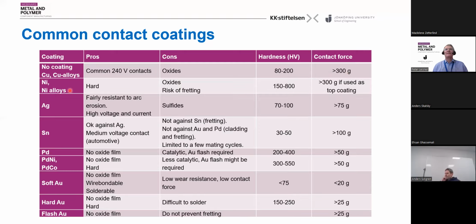Then you can use a nickel coating or nickel alloy coating. And again, talking about nickel and nickel alloys, it's a big difference in hardness and properties of these. Anders will come back to this in more detail. But these are relatively hard or hard coatings, also oxides, and also need a high contact force if they're used as the top coating. Then we have silver, which is popular for high power contacts or high voltage contacts. It could form sulfides on the surface, not so critical when you have high voltages. It's relatively soft and only needs, let's say, a lower contact force. Then we have tin. It's okay in most cases to have silver as the counterpart. Due to the softness, it's usually used in situations where you only have few mating cycles, usually what's called the stationary contacts. It's very soft.